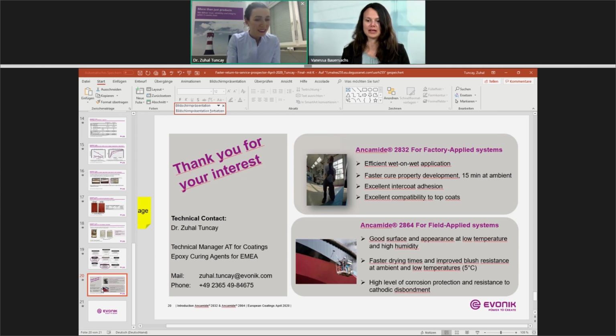Another viewer would like to know what is the thickest you have successfully applied each system? Sorry, can you repeat it again? Yes, sure. What is the thickest you have successfully applied each system? Like you see on the cathodic disbondment test, we applied 600 mils, but in 3 layers. Above 600 mils, we didn't test it, but with that thickness, we didn't get any issue. Okay, perfect.